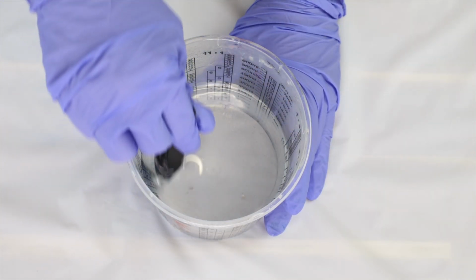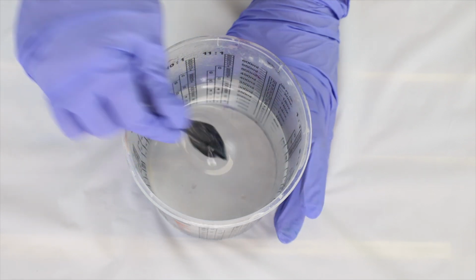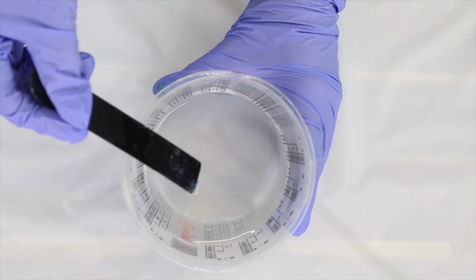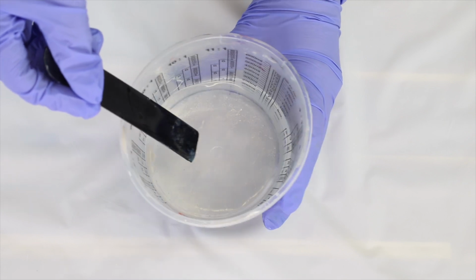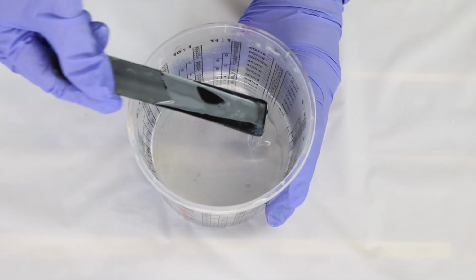If it's still foggy or if it's still got those tiny bits of separation, the ribbons where the resin and the hardener haven't mixed, you need to keep mixing. And it's incredibly important that you mix. Another thing that you can also do is let your resin sit for a little bit.